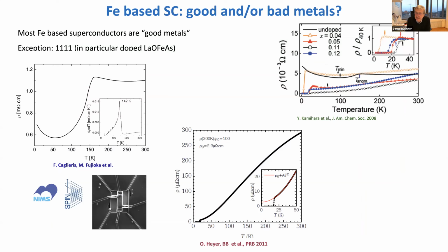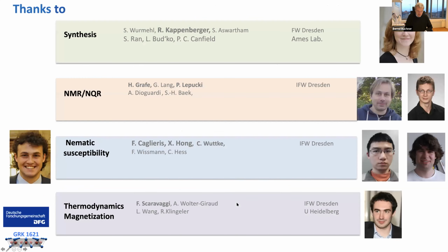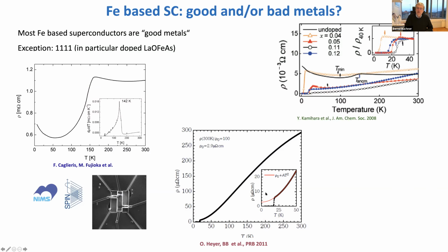Good or bad metals? Well, let's take this as a starting point. I think most of these iron-based superconductors, if you just look at the resistivity, behave like rather good metals. This is an example from our own work. This is lithium iron arsenide, which has a small residual resistance, more or less T squared at low temperatures, and a large resistance ratio. But there is one exception, and this exception is indeed these 1111 type superconductors.